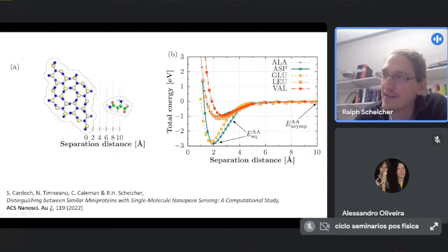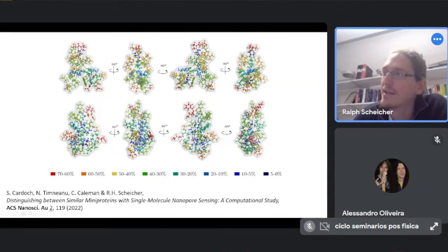So we investigated how all the different amino acids, all the 21 different amino acids, interact with silicon nitride through some kind of density functional theory calculations. So it follows a Morse potential here. And we then obtained the binding energy for all of them. But of course, not all amino acids in these different mini proteins are equally distributed on the surface. Some of them are deep inside the protein.